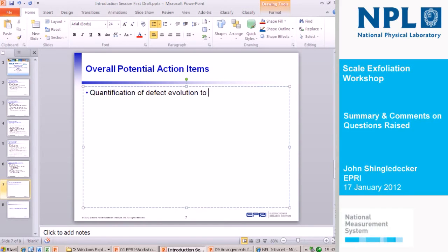Yeah, you have porosity forming at the interfaces, and maybe also distributed inside the scales, and how the interface weakens as a result of that. But you'd also need some guidance in there as to what parameters you're trying to measure, what parameters you're going to use to calculate the effective defect size. So there needs to be some protocol in place.